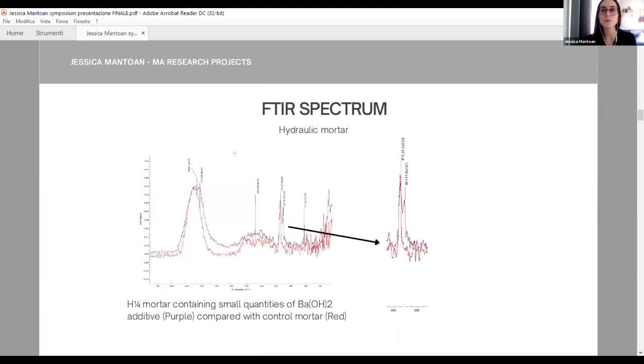Starting with hydraulic mortar, we can see that the spectrum of my mortar containing barium hydroxide, which is the purple one, and the control mortar without any additive, which is the red one, show a quite similar trend, with similar peaks at the same wavelengths. But most of all, the main difference is about 800 cm⁻¹, where we can see in the purple mortar, so the one with the additive, a particular peak, which corresponds to the presence of barium carbonate.